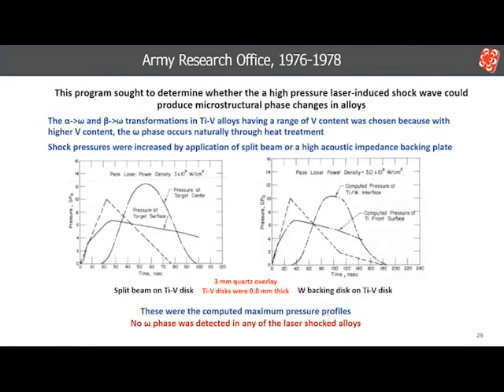In the same time period, we had a small program from the Army Research Office to determine whether pressure-induced phase changes could occur during laser shocking of some alloys. We chose the alpha phase to omega phase and the beta to omega phase transformations in titanium-vanadium alloys to investigate this possibility. These transitions were observed by others at static pressures above 9 gigapascals.